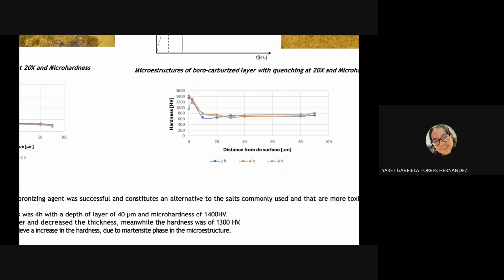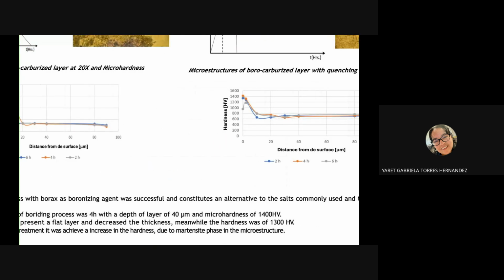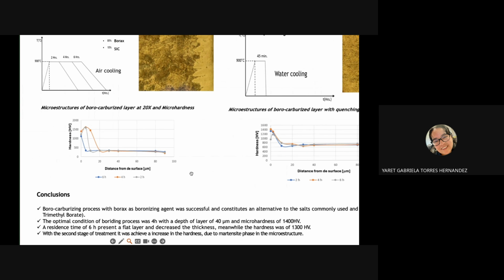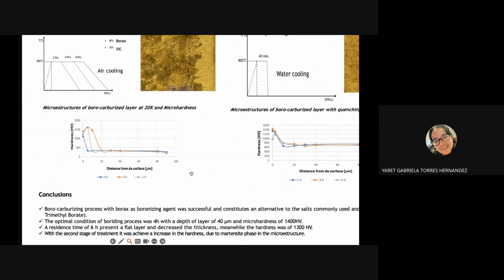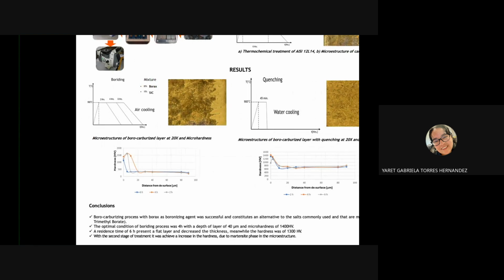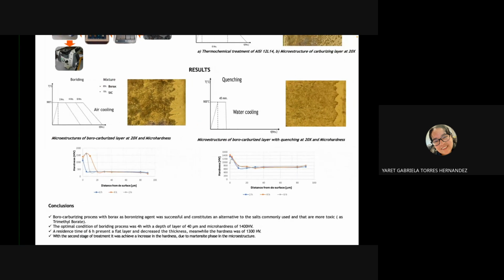Conclusions. The borocarburizing process with borax as a boriding agent was successful and constitutes an alternative to the salts commonly used, which are more toxic, such as trimethyl borate. The optimal condition of the boriding process was 4 hours with a layer depth of 40 microns and a microhardness of 1,400 HV.